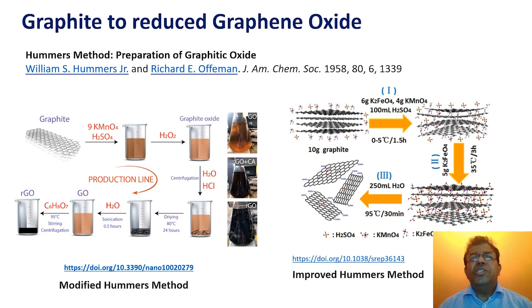The most commonly used top-down methods for producing graphene from graphite suffer from a quality versus quantity trade-off. There are two methods for producing graphene from graphite in large quantity. The often used modified Hummers process involves extensive oxidation. Still, the resulting graphene oxide can be thermally or chemically reduced to yield reduced graphene oxide nanosheets that retain some of the defects and oxygen-containing functional groups. In contrast, pristine graphene is exfoliated from graphite, often in a liquid medium, with sonication or electrochemical or high-pressure exfoliation.